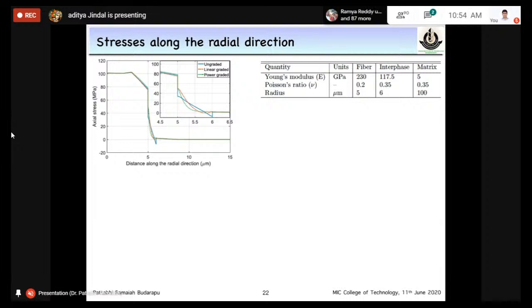So 0 to 5 indicates the fiber, 5 to 6 indicates the interphase, and beyond 6 is matrix. You see the properties sharply dropping. From 5 to 6, the properties vary — on one side you have a large stress, and on the other a very small stress, dropping from 50 to close to 0.